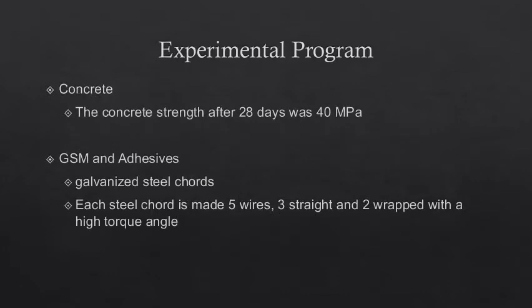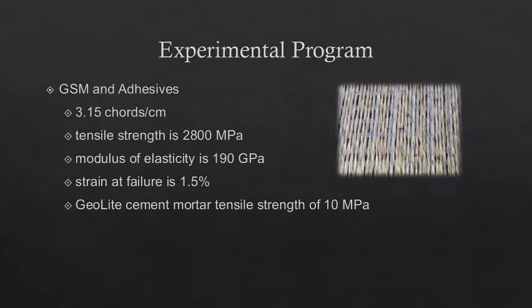In terms of material properties, the concrete strength at 28 days was designed to be 40 megapascal, and when we tested, the average was around 40 megapascal. The GSM sheets and adhesive used are from Kerakoll in Italy. It's composed of galvanized steel cords. Each cord is made of 5 wires, 3 straight and 2 wrapped with a high torque angle. This is the sheet that we use, and we can use it with epoxy or mortar. In this study we use mortar to attach this sheet to the concrete surface.